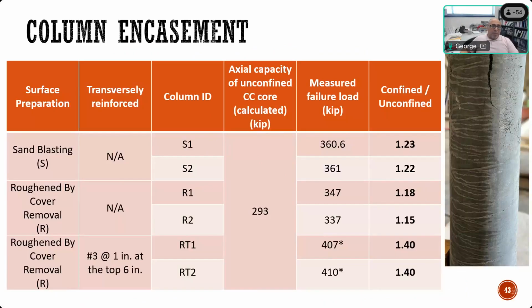Axial capacity is supposed to be 293. That's for the original one, and after adding this UHPC, we ended up increasing the capacity significantly. And actually, for the last 2 columns, we stopped the test because we maxed out the capacity of the loading frame, so it can even go further than that after adding the reinforcement at the top. The reason we decided to use reinforcement at the top is that in the first specimens we found that we get cracks at the top, so we added additional reinforcement that helped significantly increase the capacity. So we're exploring what is the best and most efficient way to use UHPC, even in conjunction with adding some reinforcement, if that will help improve the performance.